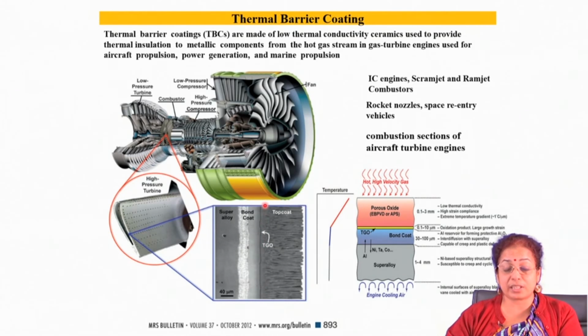Thermally grown oxide layer is also part of the whole system. Whenever you expose the system to air or maybe aqueous media, depending on the media, there will be an oxide layer formation, and that is called the thermally grown oxide layer. It basically protects the surface from further oxidation, but it is not of constant thickness; it increases with time. As you go on increasing the time, the thermally grown oxide layer thickness grows, and when it reaches a thickness of 5 to 6 micron, the coating fails.